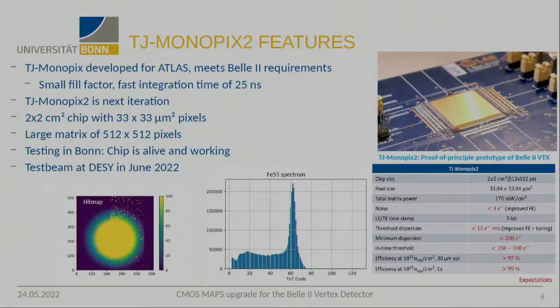So we want to use the TJ Monopix or derivatives of it. It was initially developed for Atlas, but the specifications meet the Belle II requirements with up to 5 times 10 to the 15 neutron equivalent per square centimeter. It has a small fill factor and a fast integration time of 25 nanoseconds. We might get along with a slower integration time, but at least this is very much what we need.